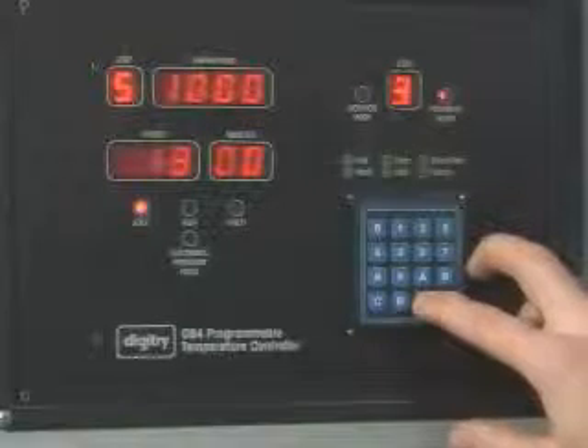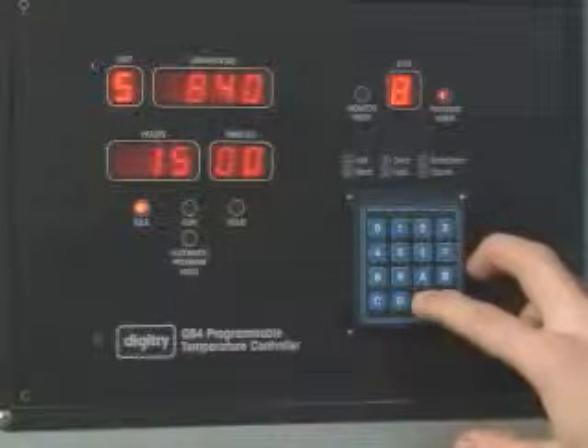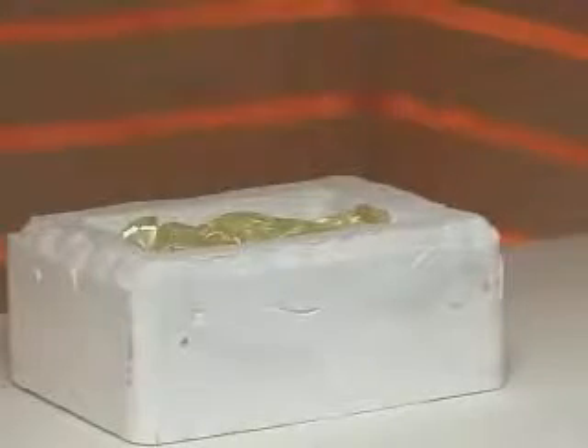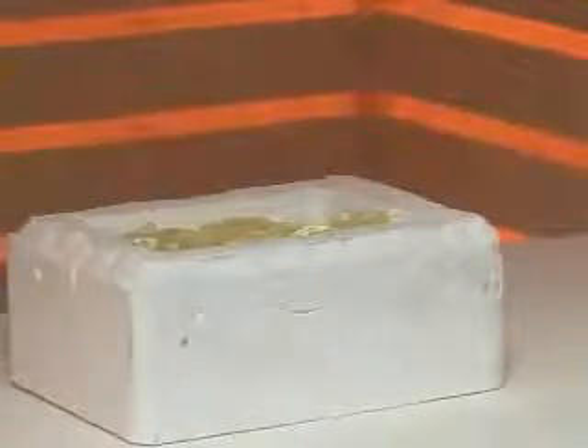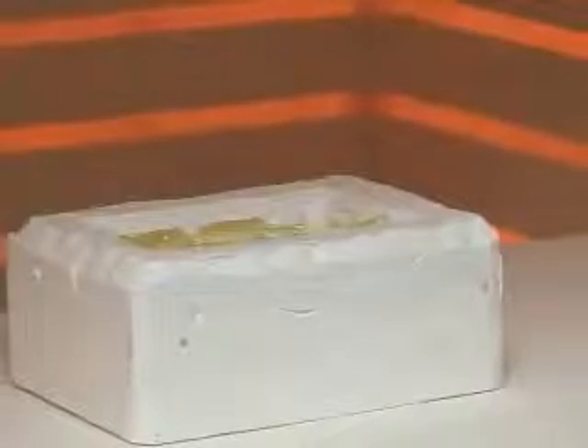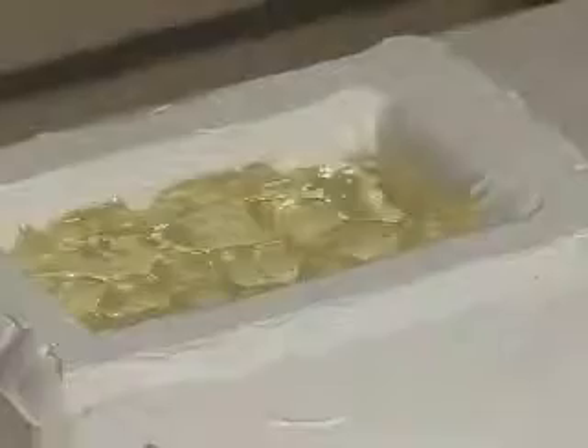The mold is filled to overflow because as the glass softens, it will take up less volume and settle downward into the mold. An electronic controller is adjusted to gradually heat the mold with the glass inside to a temperature of about 1400 degrees. Once the temperature has been reached, it takes about 2.5 or 3 hours for the fragments of glass to soften and fuse to each other and to gradually settle into the mold. As they do this, bubbles gradually rise to the surface and pop. The glass settles completely into the mold to fill all of the recesses and crevices.